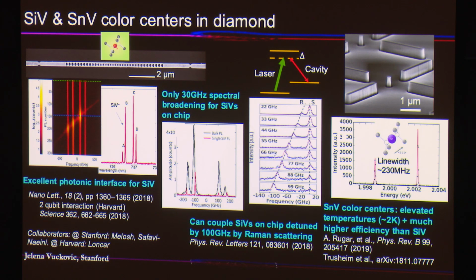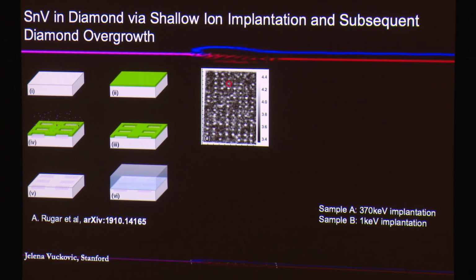You get more photons out because it's detuned from some multi-phonon non-radiative process. So we characterize that, and we're also working actively on methods where we can incorporate these color centers into the lattice without damaging the lattice. Because I mentioned a few slides back, one of the biggest issues and biggest questions, and this is a great topic for material scientists, is how you can make a regular lattice of these qubits, quantum emitters, with as close to 100% yield as possible, right?